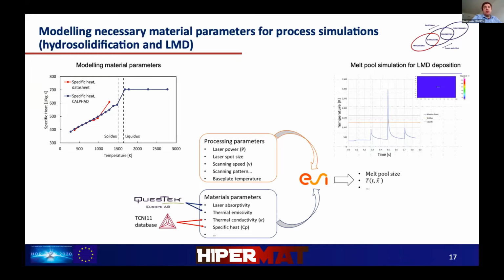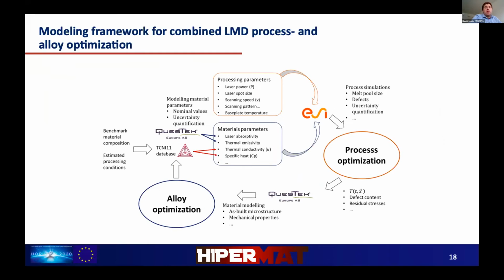And feeding this into the ESI simulations, we can then get, for example, melt pool size or time temperature profiles as shown here. We can move to the last slide. And moving forward in the project, the idea is to really work with this combined framework for LMD process and alloy optimization, where the first steps we've shown on the previous slide was generating input parameters, but then utilizing these simulations for process simulations would allow for a more accurate description of the time temperature profile that is seen during the LMD deposition, which we can then plug into our other material models to work on predicting as-built microstructures and mechanical properties, which could then help further alloy optimization, etc. And this could then be a repetitive loop.